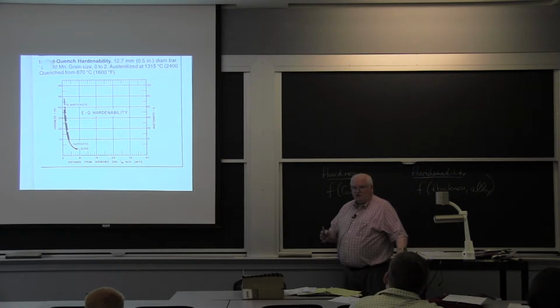Well, the problem is I want to make something that's strong, that's 2 inches, 4 inches, 6 inches thick, so I can make a plate that has high strength. Okay, so this is the maximum I could get with a 1020 steel, about 40 Rockwell C. I could get 60 Rockwell C if I had a higher carbon, that's hardness, but I can't get much deeper with high hardness. So what do I do?